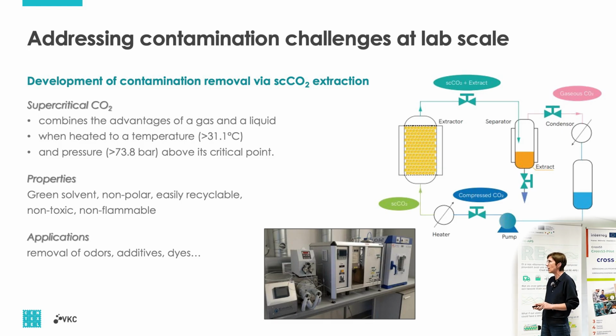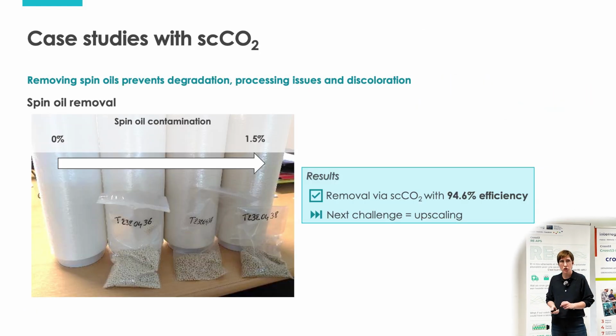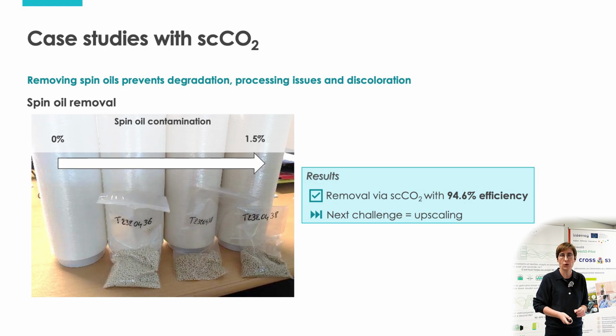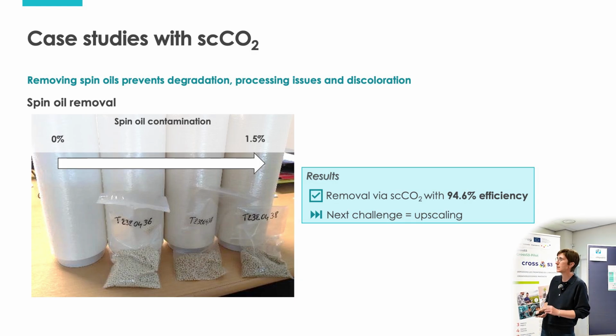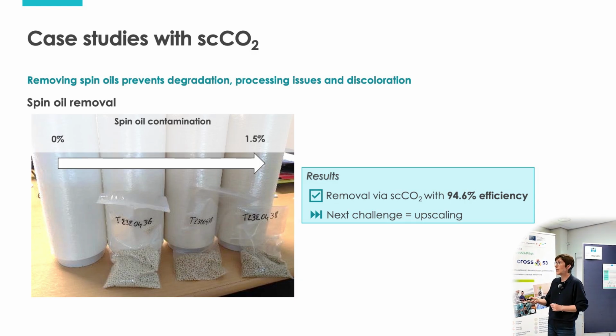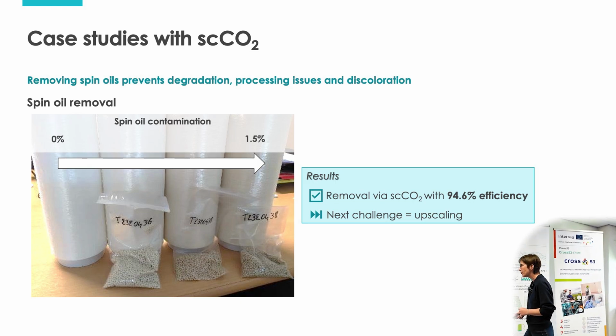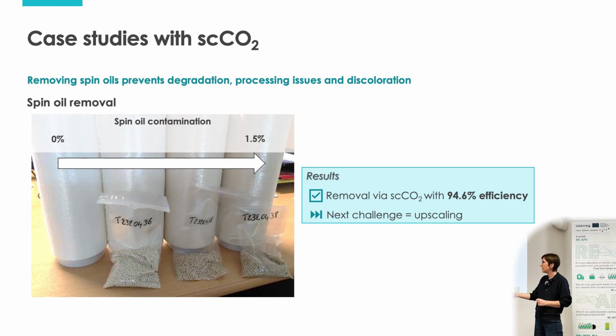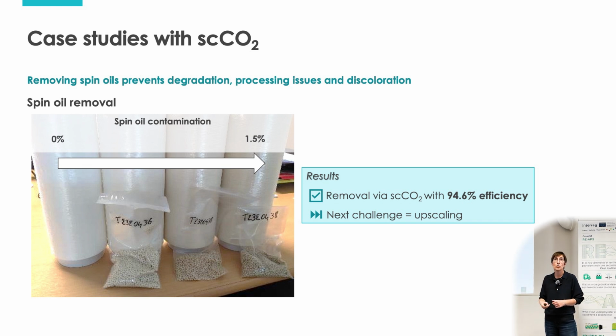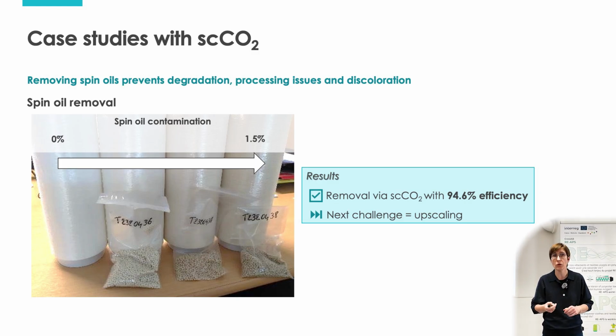Just to show you one example, this is the impact of the spin finish that you apply during your fiber extrusion process, which is of course important. So we applied from 0 to 1.5% of it, and the color is maybe not very well seen, but this is a whitish one, and you see if you try to recycle this material, due to the presence of the spin oil, it was yellowing. So your polyester material yellows due to the spin oil.